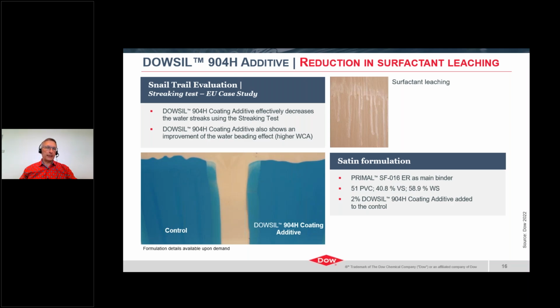In the lower left picture, and it's not always easy depending on the screen and the presentation to see the difference, but you can see a clear difference in the film appearance with and without the use of 2% of this additive in an acrylic-based formulation using the simple water drop test, in which a couple of drops of water are applied on the freshly dried film, left on contact for a while, and then allowed to run out. And you can clearly see traces of these water droplets in the control formulation, but not in the formulation containing the snail trail reduction additive.